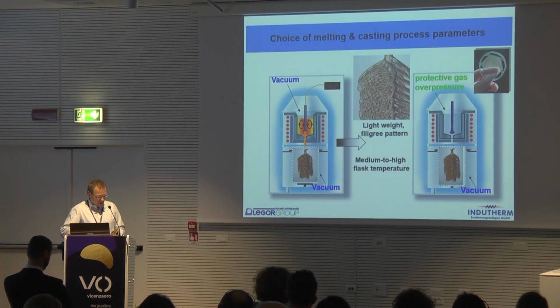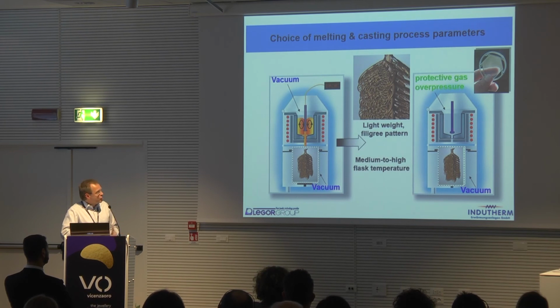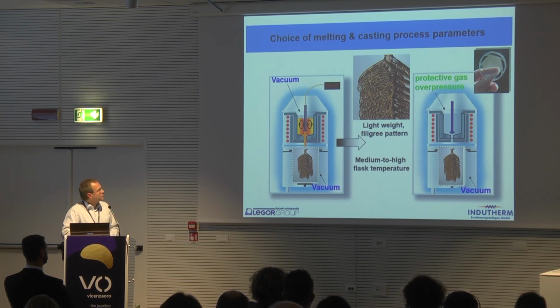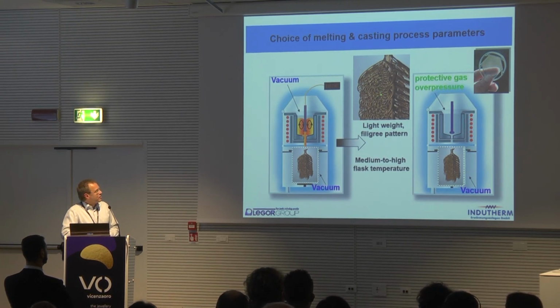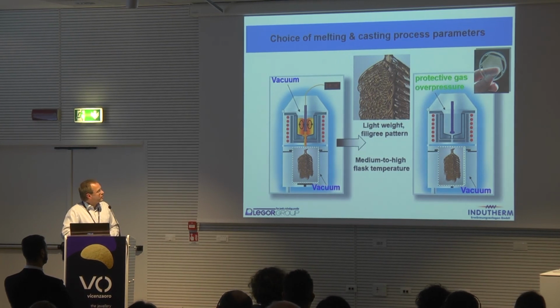As a general rule, I want to close with some two extreme cases here. When we cast filigree items, lightweight parts, where we typically use high or medium to high flask temperatures, yes, we can do that. If we pour into molds at high flask temperature, there's always a risk for reaction with investment. But if we want to fill the parts, then there's no way out. We have to do that. And the risk for reacting with the investment will be, in this case, low, because the volume of the more filigree parts is not so high. So the heat up of the investment will be less. So in this case, going to medium to high flask temperatures is mandatory.